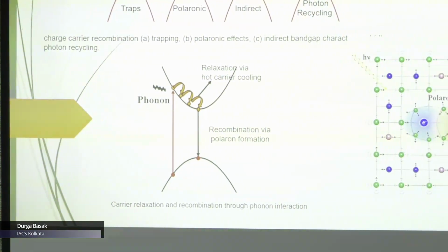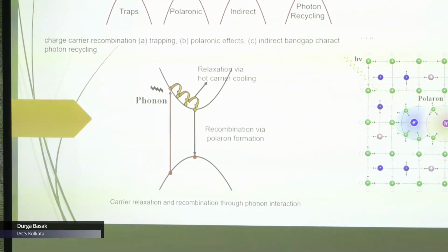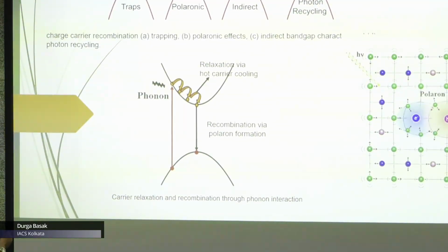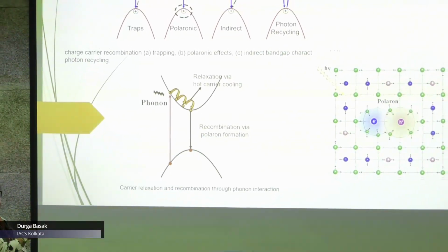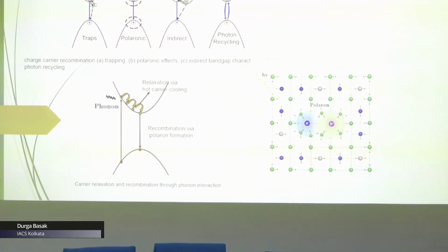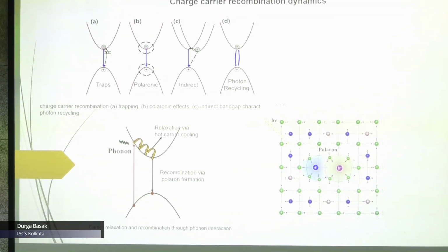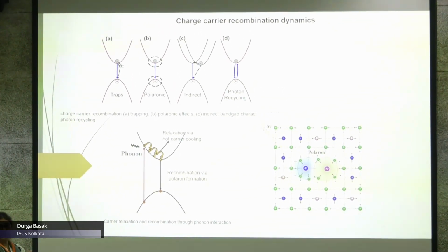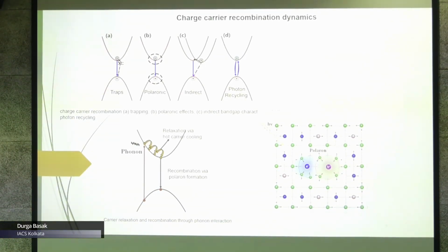The other is recombination assisted by polarons. This I am going to discuss later, just finishing this. And another is the indirect band gap effect. How does this indirect band gap recombination happen? Due to the Rashba effect or spin orbit coupling, the valence band and the conduction band are split. If the splitting is not the same, then an indirect band gap is generated, and there phonon assisted carrier hopping happens, and then the recombination happens. And next is photon recycling. This happens in highly crystalline, pure substances, where a generated photon is reabsorbed and again re-emitted.